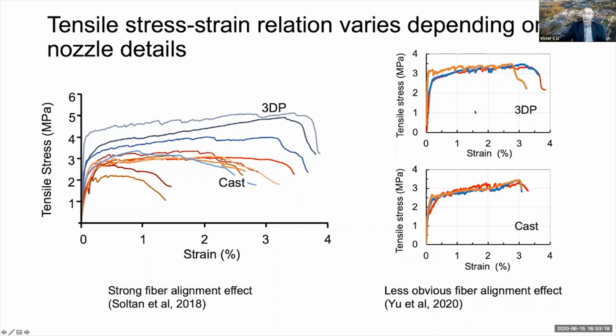On my right, you can see that the 3D printed specimen compared to the cast specimen of the same material shows roughly the same strength and same ductility, about 3% strain capacity. This is 3D printed by a robotic arm with a customized nozzle. So we see that the details of the stress strain behavior of the 3D printed ECC, while they all show good tensile strain capacity, the exact behavior depends on the print parameters and the nozzle details, including its geometry.